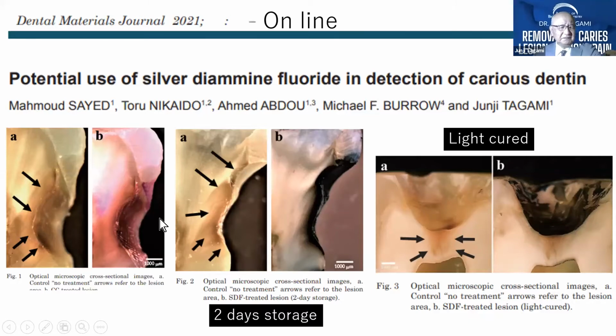In this paper, we cut the caries cavities in halves, and one half is stained by the conventional dye solution, and another half is applied with the SDF. And afterwards, we observed the blackening of the region, and we compared between the conventional staining and the SDF staining. As a result, the SDF tended to stain much deeper than the caries detecting dye solution. If you apply the light onto the SDF applied surface, only the surface area is very strongly blackened, but the penetration of the staining is very limited.